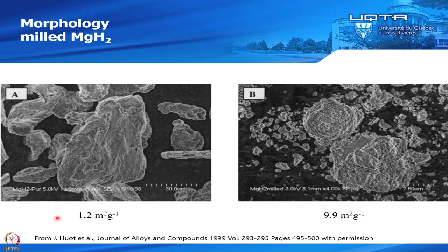And you see that the specific surface area here was only 1.2 square meter per gram. And by ball milling, we increase it almost by a factor of 10. But it's still not a very high specific surface area. You increase it by an order of magnitude, but it's still not very high like you see in carbon nanotubes or graphite, where you have 100 to 1,000 square meter per gram.